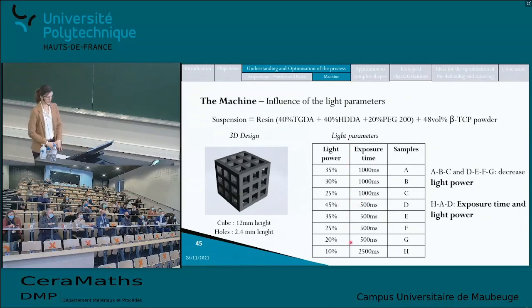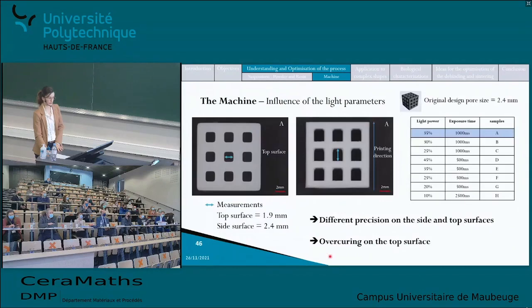So what appears here for the first samples that were observed with a microscope is that the measurements made on the top surface, so the measurement of the size of the hole, are not the same as the ones made on the side surface. So there is different precision due to the printing process on the top surface and on the side surface. And actually the precision on the side surface is quite good. So I decided to only evaluate the top surfaces of all the samples.